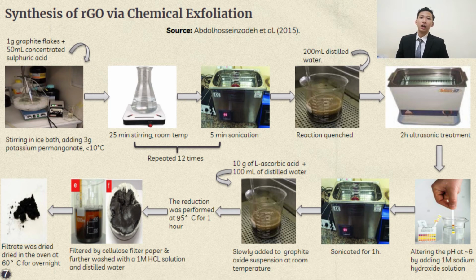Moving on to the next step, 10 g of ascorbic acid powder will be added and dissolved in 100 ml of distilled water. Then, the ascorbic acid solution is slowly added to the graphite oxide suspension at room temperature. The reduction was performed at 95 degrees Celsius for 1 hour.